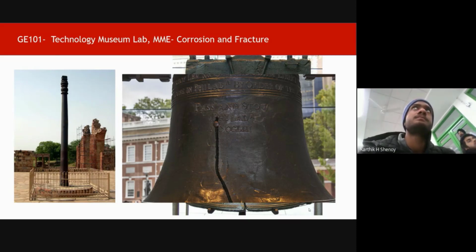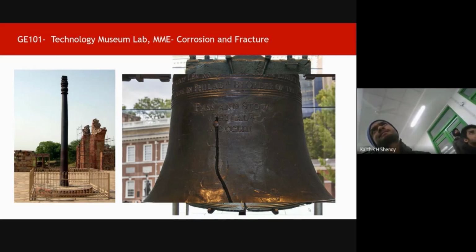If a crack has to grow, if a piece has to break into two pieces, then there will be two new surfaces, so you also need that energy. Plastic energy plus surface creation energy is needed in order for a crack to grow. If you can somehow decrease the stresses at the tip so that it is lower than the amount of resistance which the material is offering, a crack cannot grow. And this is what they did: they blunted the crack by putting those pins and hammering them.